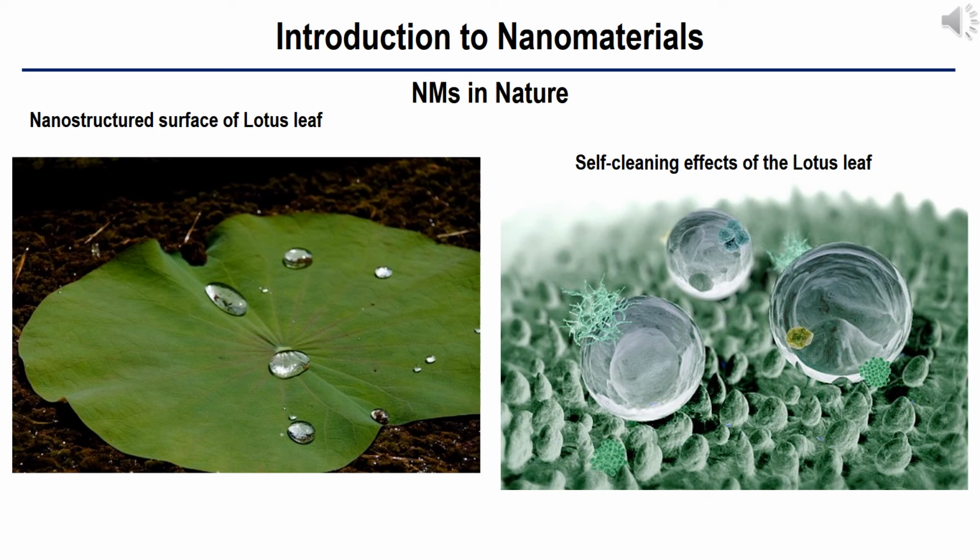By altering the surface structure of the leaves while keeping their chemical composition approximately the same, the researchers were able to confirm the importance of the lotus leaf's nanoscale hair-like structure on its self-cleaning ability. Researchers did this by heating the leaf until the nanoscale hair-like structures melted, at 150 degrees Celsius, coating the leaf surface.